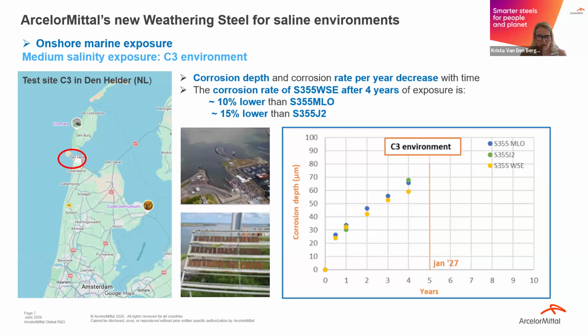So in product development, after testing mechanical properties and weldability, now we focus on the corrosion performance. So coupons of this new industrially produced saline-resistant weathering steel are exposed to accelerated corrosion tests, but also different real-life outdoor tests in specific environments. The environments are classified in corrosivity classes, where you have different humidity and a different load in chloride. So here we split up the exposures depending on the corrosivity class.